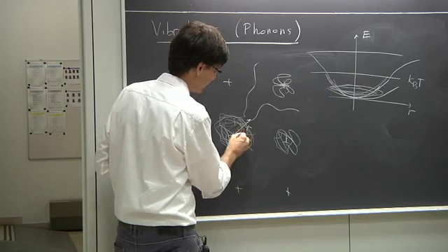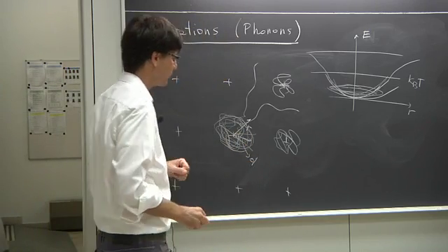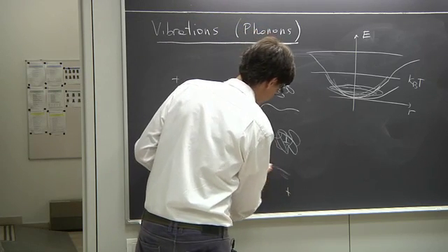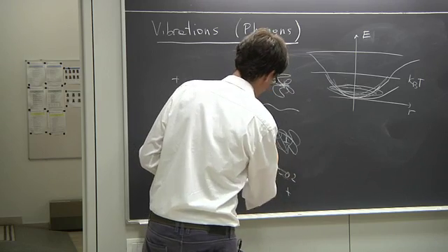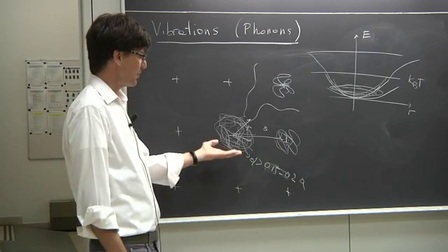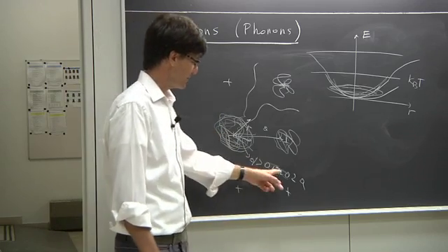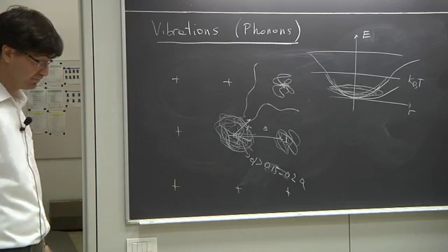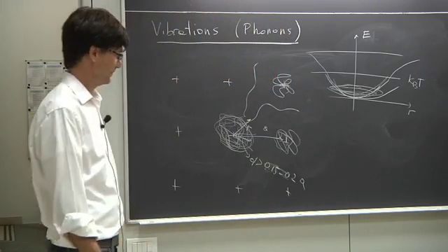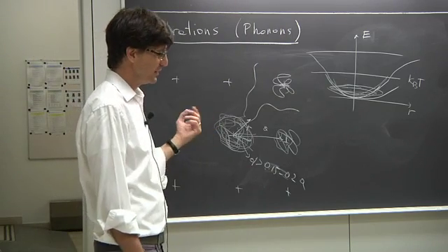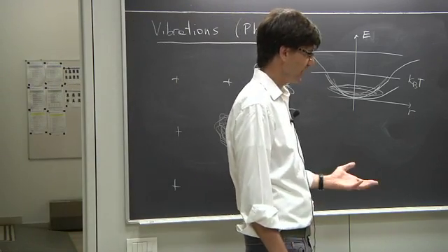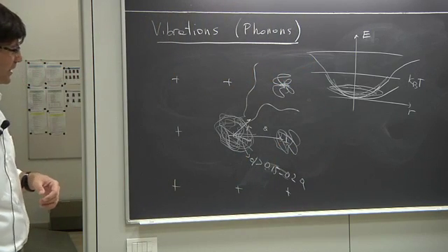So the rule states that as soon as the amplitude d of fluctuations of a particle around the nucleus exceeds something of the order of 15 to 20%, well, 0.15 to 0.2 of the interatomic distance a, as soon as the temperature is such that this condition is violated, that is, the distance becomes larger than 15-20% of the interatomic distance, 99% of the materials will melt. I think it's nice to mention it because it gives you an idea of when you should expect that thermal vibrations essentially kill the crystal and lead the system into a fluid, into a melt.